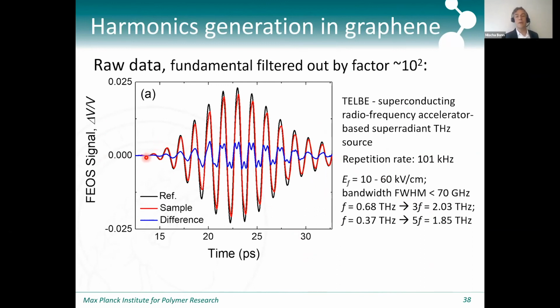So the black line here is the incident field, going through the bare substrate. The red line is the field, so this is, again, this electro-optic sampling, the field going through the graphene on the substrate, where we have filtered out the fundamental by a factor of 10 to the 2. And if we take the difference between those two, you can see the blue line here, and you can actually see the harmonic oscillations on the fundamental oscillations in the field.